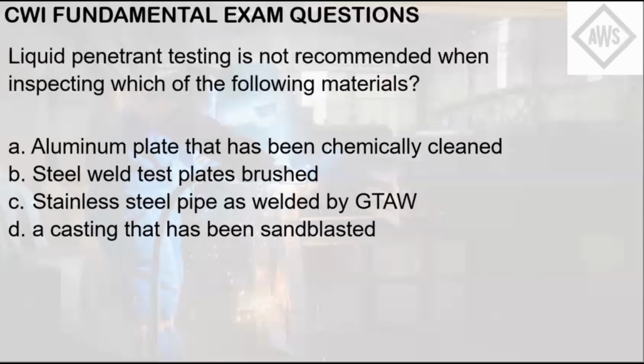Sandblasting breaks off or peens the surface, which can close the openings in the surface necessary for capillary action. So if you sandblast the surface of a metal, dye penetrant testing will not be possible because you basically broke off all the openings necessary for the capillary action, or the liquid rising to the surface, to occur. So the answer here is letter D, a casting that has been sandblasted.